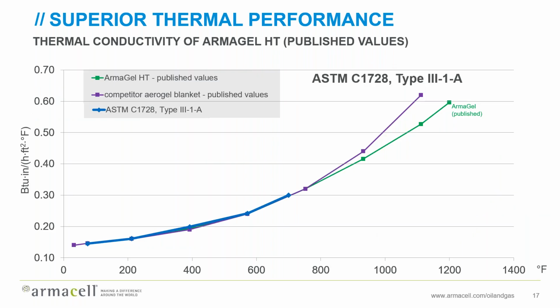Just to show you the curve from the ASTM standard, the blue line is the ASTM, what you have to meet. Competitor blankets meet that, we meet that, of course, otherwise we wouldn't be able to sell it as compliant with ASTM C1728. But what's quite interesting is as the temperature increases, our thermal performance relative to other aerogel blankets gets better. So we have a very high performing blanket, particularly at those elevated temperatures.